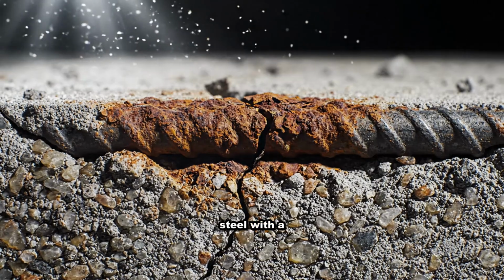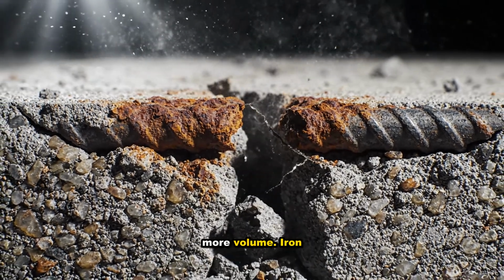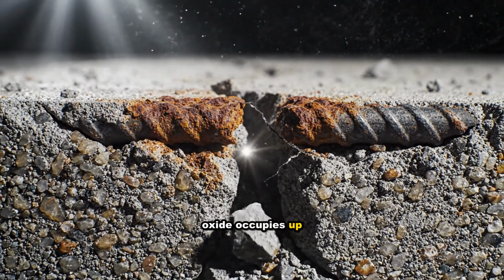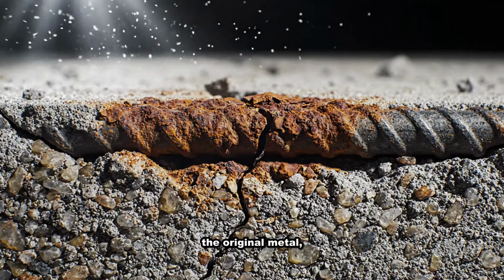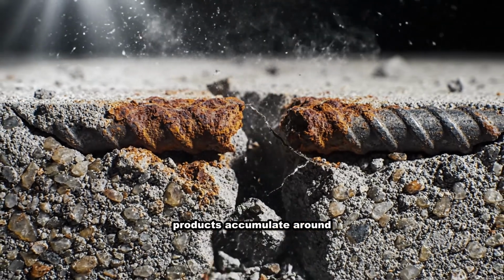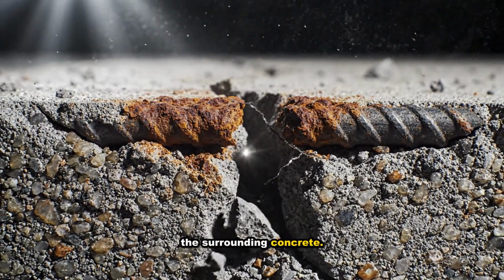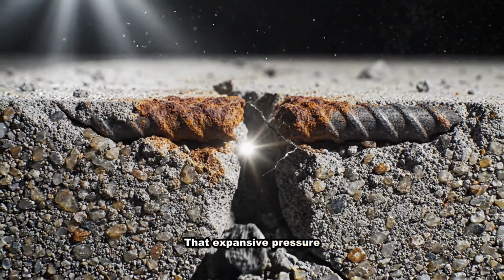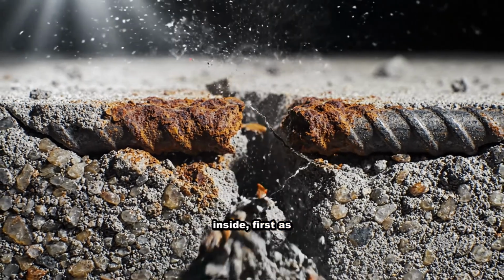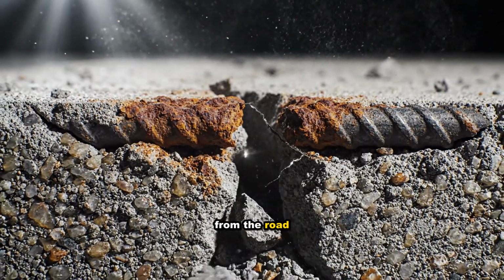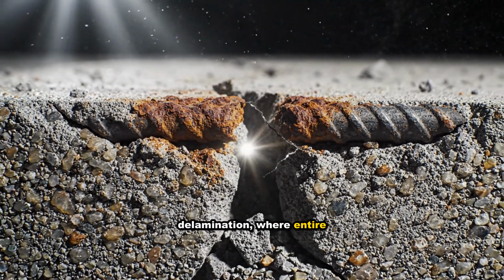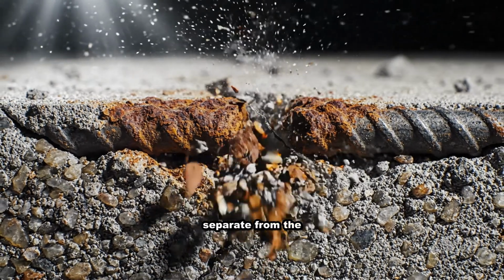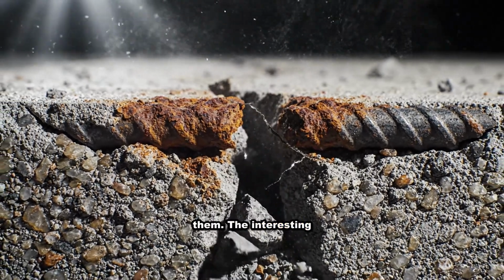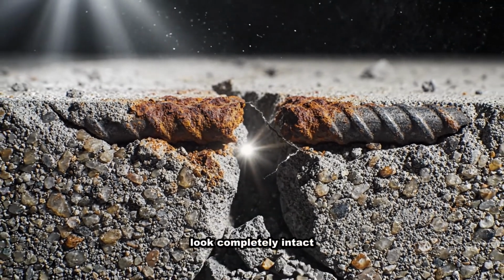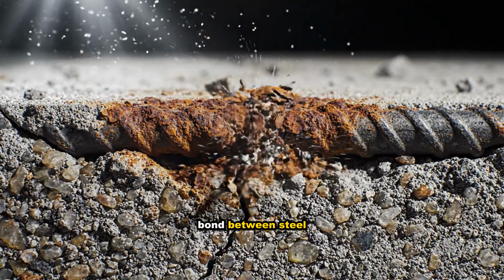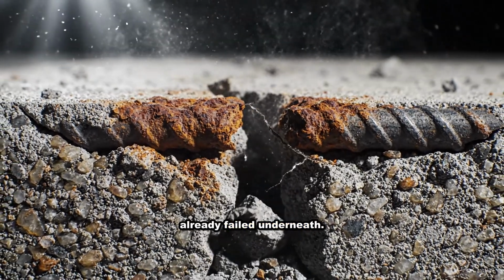Rust is not steel with a coating removed. Rust is steel with more volume. Iron oxide occupies up to 6 times the volume of the original metal, so as corrosion products accumulate around the bar, they push outward against the surrounding concrete. That expansive pressure cracks the concrete cover from the inside, first as hairline cracks invisible from the road surface, then as delamination where entire slabs of concrete separate from the rebar mat beneath them. The interesting part is that the concrete can look completely intact on a visual inspection, while the bond between steel and concrete has already failed underneath.